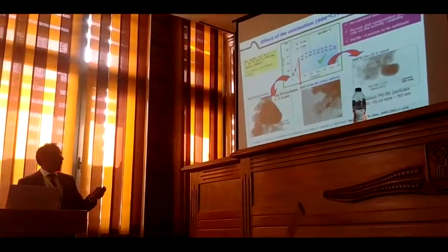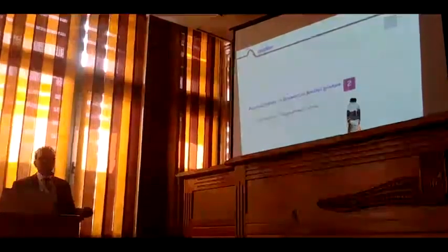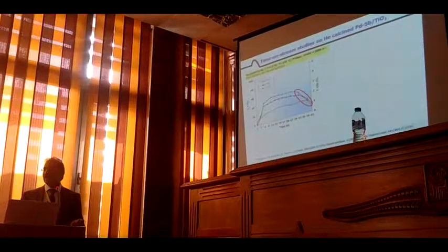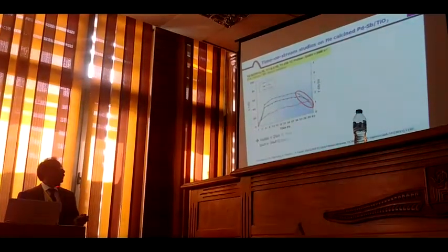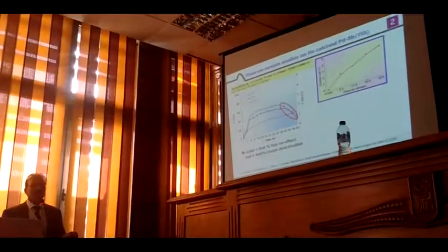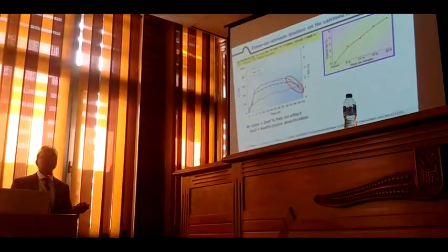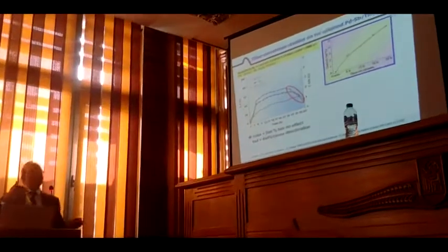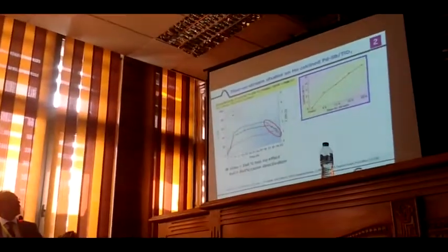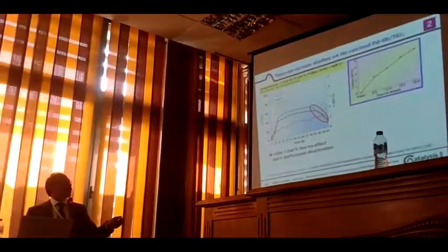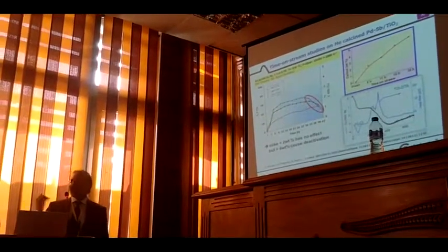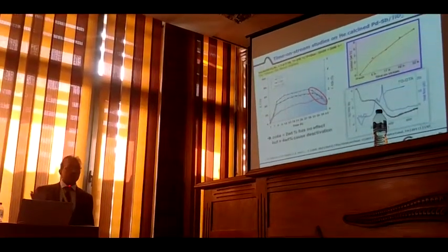So we can see we have a deactivation. So the helium-calcined one also undergoes deactivation. And what is the reason for deactivation? This is due to coke formation. We estimate the coke as a function of time. The coke is increasing with increasing reaction time. And when the deactivation is inevitable, so you can't avoid it, you have to look for a regeneration procedure.